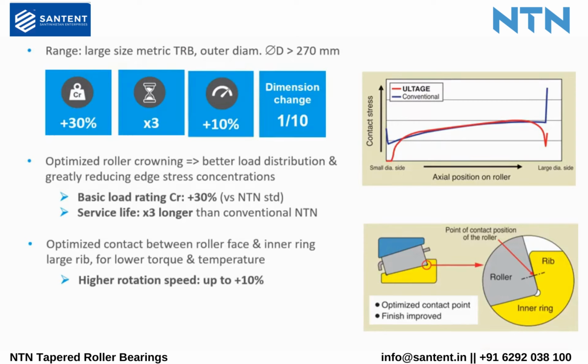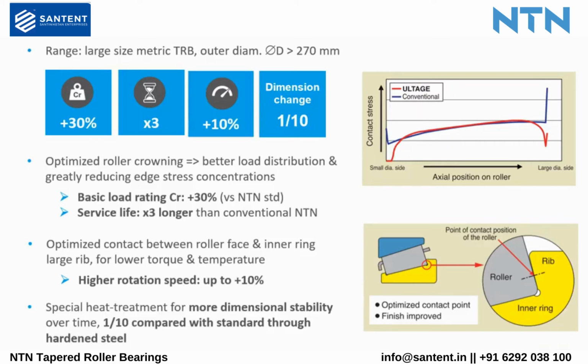ULTAGE is also an optimization of the point of contact between the large face of the rollers and the large rib of the inner ring, as well as better surface condition for less torque and heating, which made it possible to increase the rotation speed by 10%. And finally, ULTAGE tapered roller bearings use through hardened steel with a special heat treatment to drastically limit the deformation of the bearing rings over time. It is 10 times less deformation than for a through hardened steel with a standard heat treatment, and 4 times less than a case hardened steel. This special heat treatment will ensure a constant performance over time.